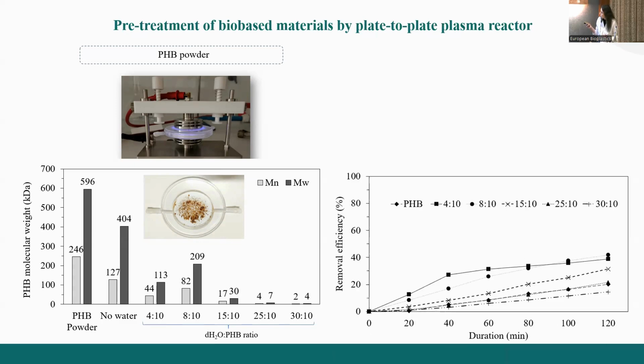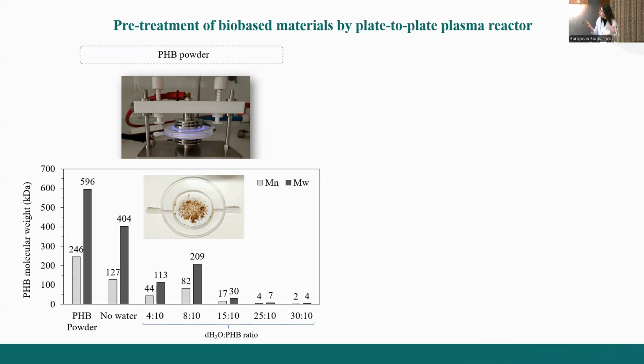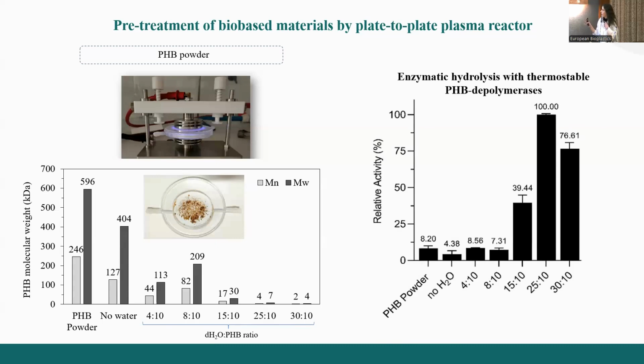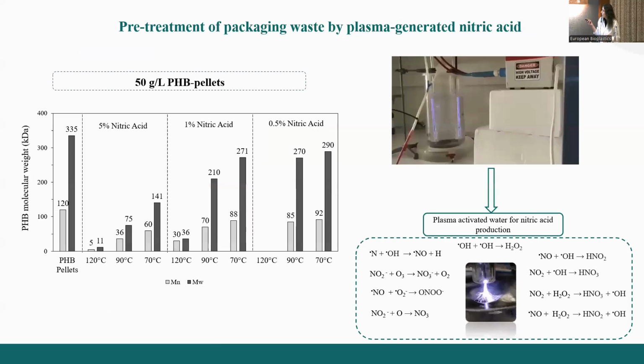So, this is also reflected in the enzymatic degradation of the PHB samples, and maybe this is attributed to the better dissolution and the more efficient mass transfer of the reactive species into the water, and especially the ozone and hydroxyl radicals, which are responsible for the oxidation of the polymer surface. And in the next set of experiments, we carried out an indirect plasma pretreatment using plasma-generated nitric acid, which was